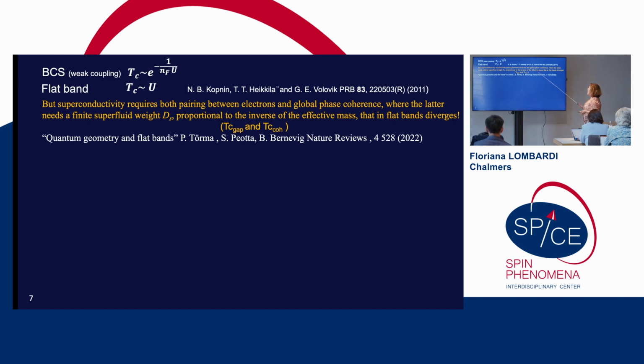But in flat band, we have that the effective mass, even though this is an approximation, as we discussed with Marco, is infinite, and then what one gets is that you don't get a superfluid weight. So in principle, if you have a flat band, your electrons are immobile, so you need a finite superfluid weight to get superconductivity. And then it has started all the field of quantum geometry, with the quantum metric that would give a finite mass to this. If this applies to magic angle graphene or other systems is still to be discussed.